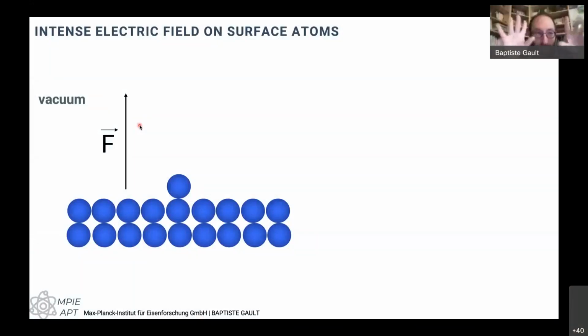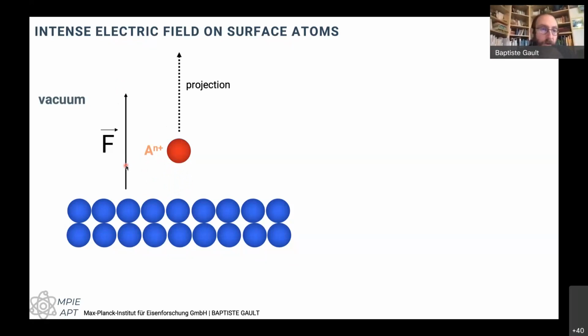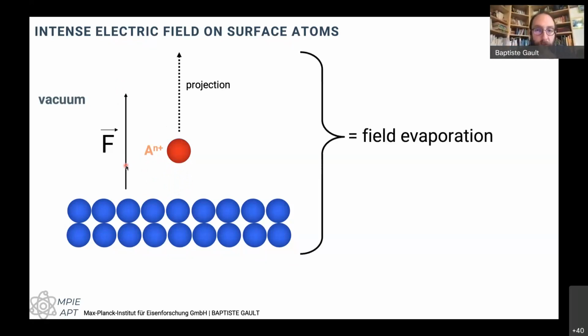Let's go back to the basic physics of how that works, because a lot of the interests or qualities of atom probe and also a lot of its drawbacks and problems actually arise from this principle. So if I take a surface and consider just a single atom sitting on the surface and I apply a high electric field, so I can just apply a high voltage onto this surface and it's going to translate to a high field right at the surface. And if the field is high enough, the surface atom can start to be repelled from the surface and potentially ionized. And now I have an ion in an electrostatic field. So as you might guess, the field is going to accelerate the ion and the ion will fly away. So it's as if it was projecting this atom, first making it into an ion and then projecting it away from the surface. This combination of desorption and ionization is called field evaporation, and that leads to the projection of these ions away from the surface.